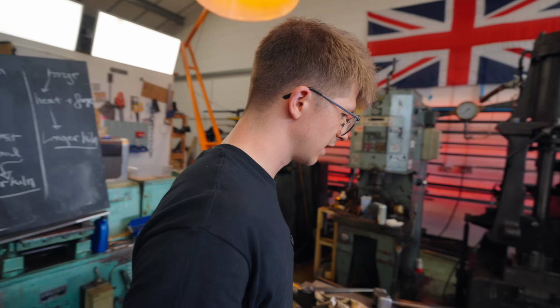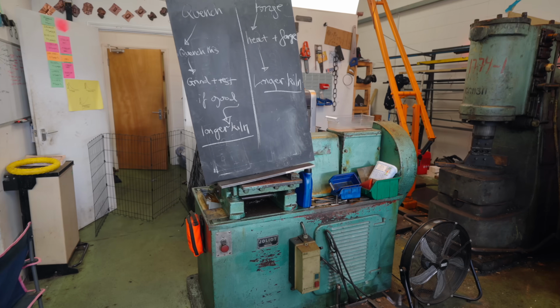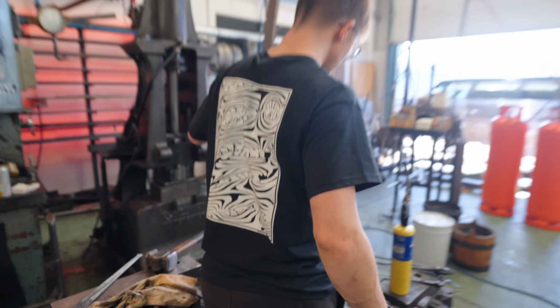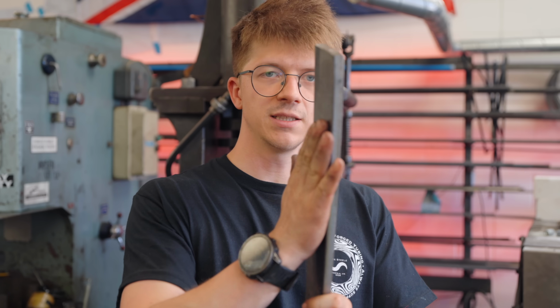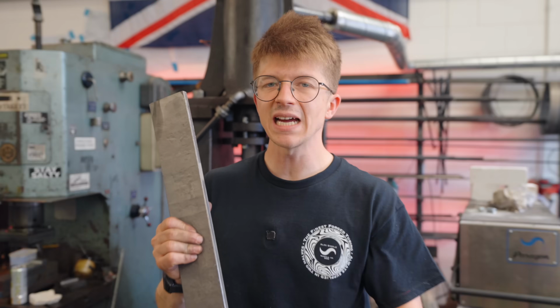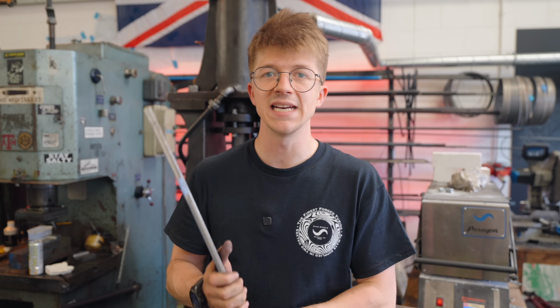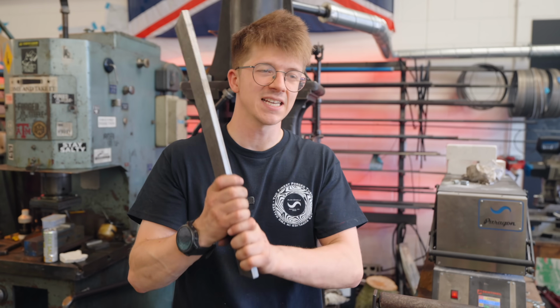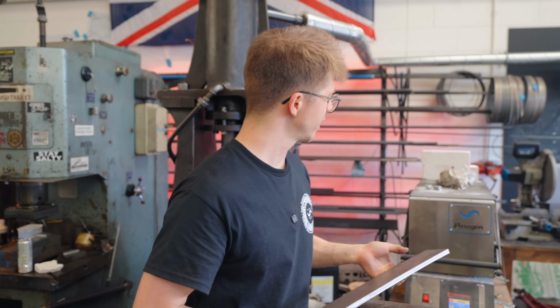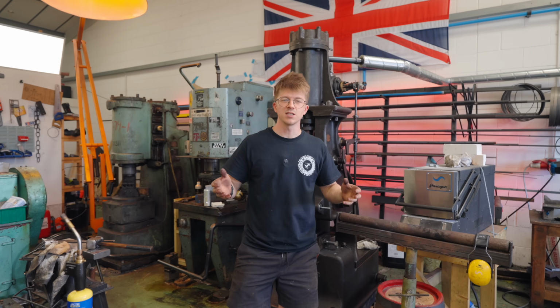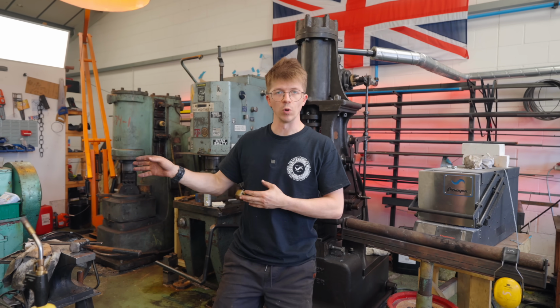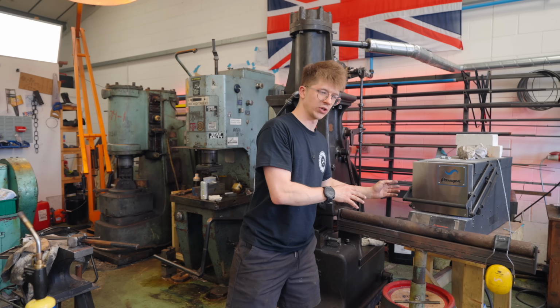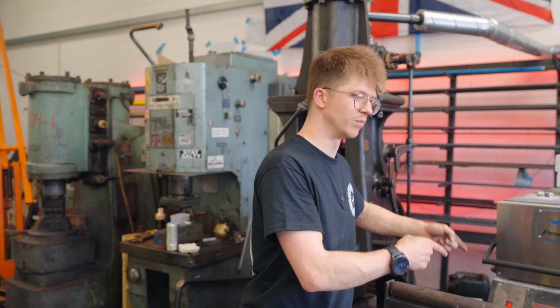Okay, I've got the definitive answer. Where did I put it? Where did it go? What have I done? Oh, for goodness sake. Here is the plan. We are going to harden and temper this big slab here, mill down the sides close to the thickness of an actual blade, and then turn it into a chopper and test it and see if it's good enough, or see if the titanium sides fall off. Because now that we know that there doesn't appear to be a massive difference with our new rolling techniques at 850 Celsius, or just bonding it and leaving it from 850 Celsius, I feel like I'm gonna get a picture of the suitability of this whole titanium to steel thing once that becomes a longer, thinner blade and we start abusing it.